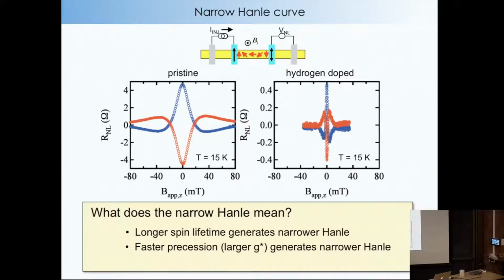This is a big problem, but over the course of a few papers between our group and Van Wees' group, we have agreed on a good way to deal with this issue. Before, I told you that when you have a longer spin lifetime, you get a narrower Hanle curve, right? So we measured the Hanle, and we said, wow, it's so narrow. The spin lifetime has shot through the roof. We were so happy.